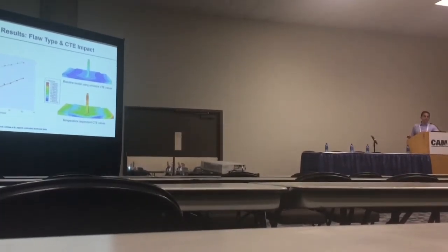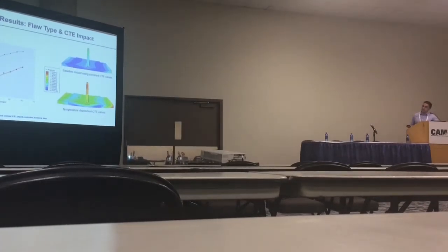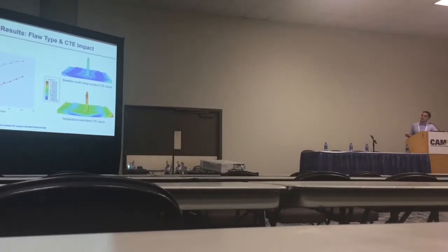Each dot represents one simulation. In this case, the model had 10 plies, and the first node released at almost 90 pounds force. It's black, meaning it's for the first flaw. Clearly, flaw number 1 is more critical than flaw number 2.